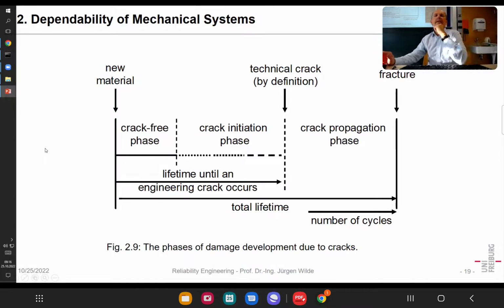And so generally in fatigue, what happens? Normally, when you load it, you have a crack-free phase when it's a new material. And sometimes, as I said, you have already inclusions, for instance some oxides or so in steels, and that means you do not have that crack-free phase. But in a good material, you have it, and then after a certain time, you have a crack initiation. A crack initiation means you have some surface profile where the step size of such a profile is in the micrometer region.